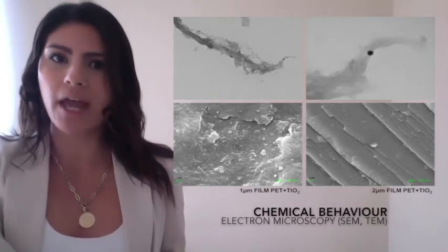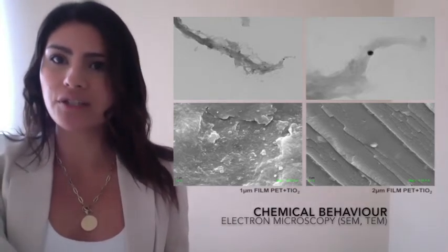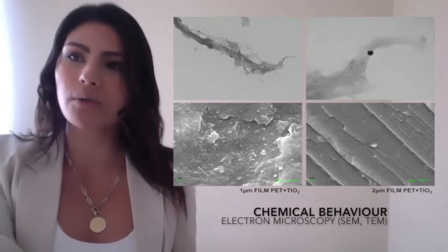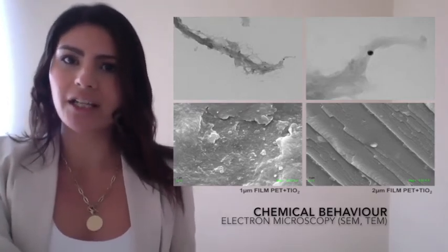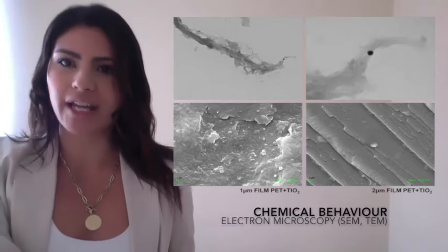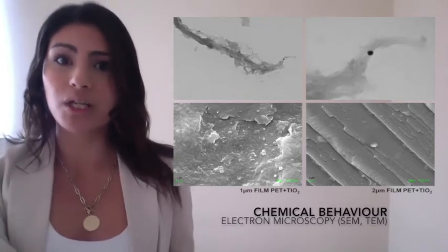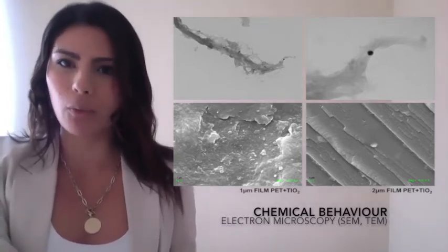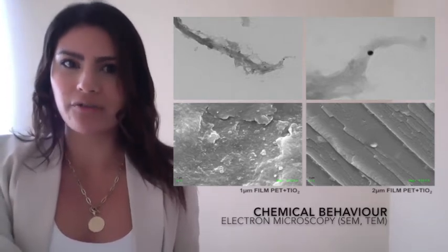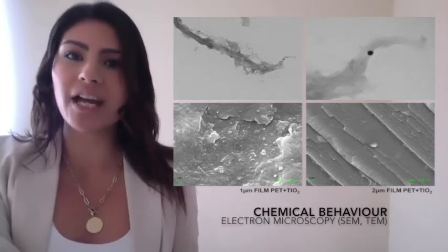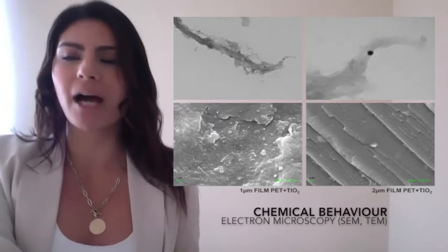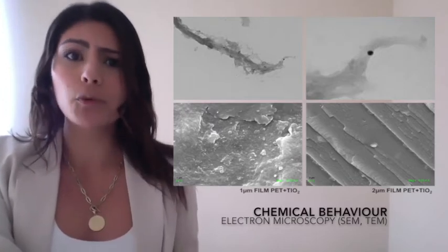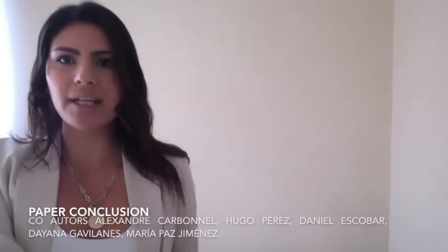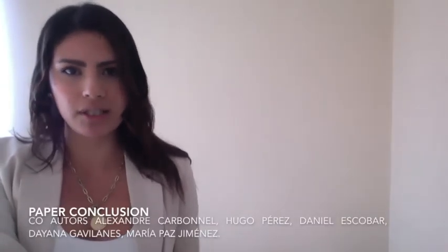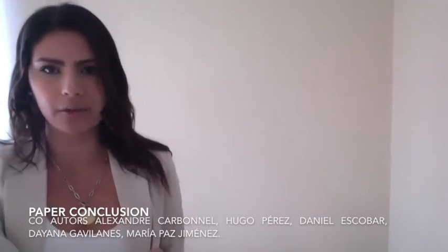Electron microscopy analysis of the samples revealed a distribution of nanoparticles throughout the film, thus validating the proposed combination of recycled PET with titanium dioxide to achieve a photocatalytic building envelope material. Greater surface roughness will increase the area of contact between the film and the air. Incorporation of 8% titanium dioxide nanoparticles results in a loss of the original viscosity and elasticity of the recycled PET.